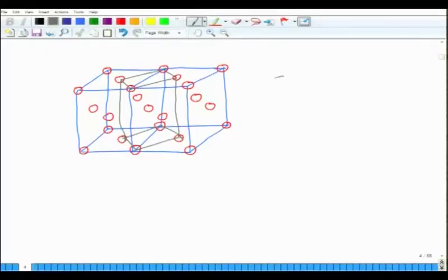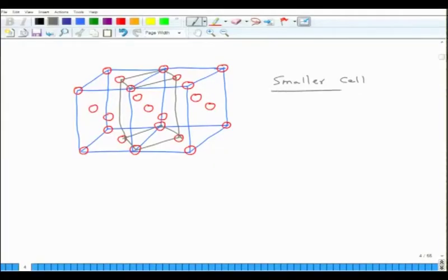So, basically we prefer a smaller cell. If you remember, I earlier told you there are two criteria: one is the smaller size, the second is the symmetry. In case of the cube you saw it does not follow the symmetry, right. In this case we can see that there is a smaller cell size which is preferred, and as a result it is defined as body centered tetragonal.